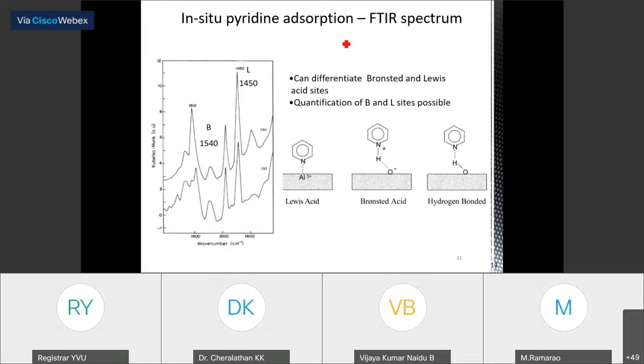It is a widely used technique. By adsorbing pyridine on the catalyst and taking the FTIR spectrum, people characterize the Brønsted and the Lewis acid sites. Typically, if there is a Brønsted acid site in the material, it will have a peak at approximately 1540 centimeter inverse. And in the case of Lewis sites, it will show a peak at 1450 centimeter inverse.